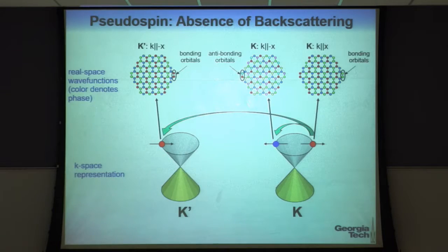Now the consequence of that, one of the consequences, is that if I try to have an electron backscatter, so this is a blow up near the Dirac point of the energy versus wave vector, okay? And those Dirac points in K space, they're curiously given the nomenclature of K, where that's a capital K to distinguish it from the wave vector, little k. So in the vicinity of this K point where the cones meet, if I look at the sense of the wave functions, well, over here, it is the bonding wave function that dominates, whereas it's the anti-bonding wave function that dominates over there. This circle is a constant energy circle in the vicinity of the Dirac point.